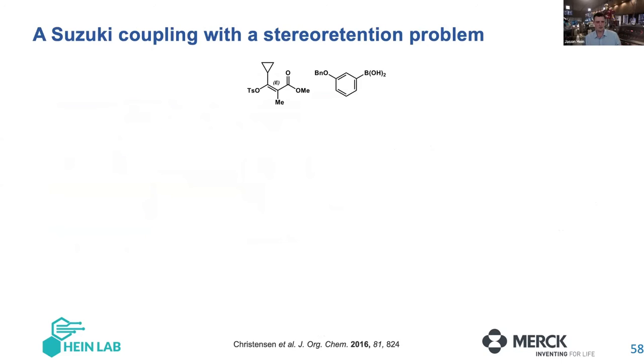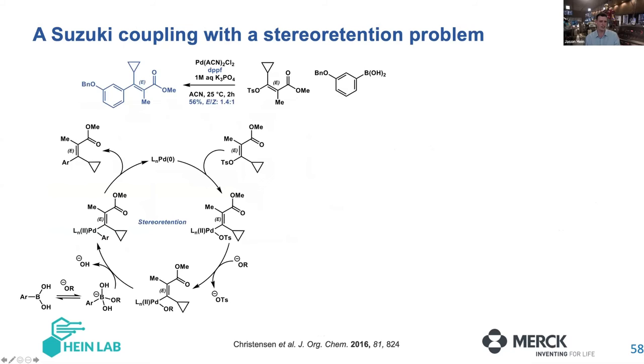As a test, we wanted to take on a very simple Suzuki reaction, using a vinyl tosylate and a boronic acid. The goal here was to have this undergo what is called a stereoretentive Suzuki coupling, where the position of this tosylate is replaced with our aryl group. And again, it goes by the canonical cross-coupling pathway: oxidative addition, transmetallation, then reductive elimination.